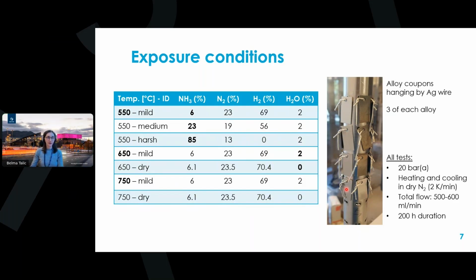We carried out the exposures at 7 different conditions as presented in this table. The temperature was varied from 550 to 750 degrees centigrade. We varied the ammonia concentration from 6 to 23 and 85%, with the remaining gas being nitrogen and hydrogen in a mixture equivalent to cracked ammonia.